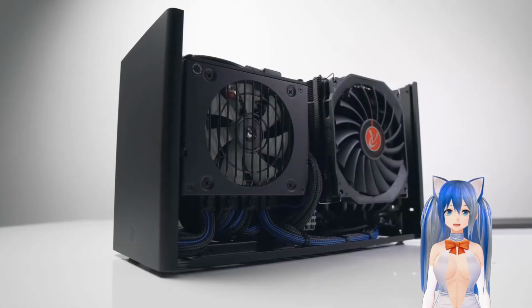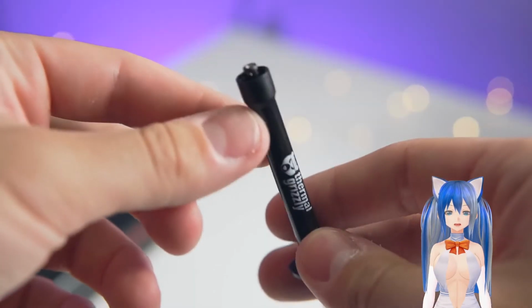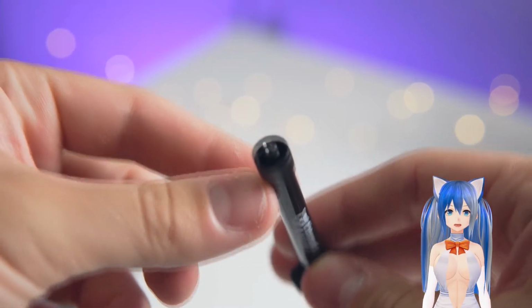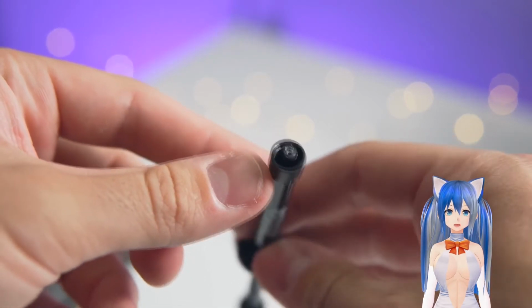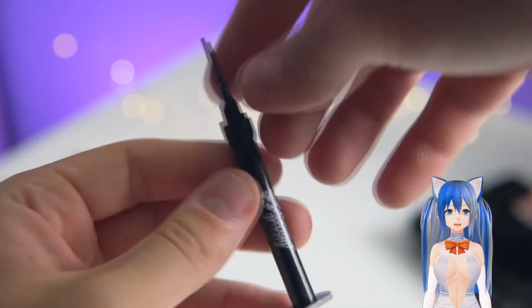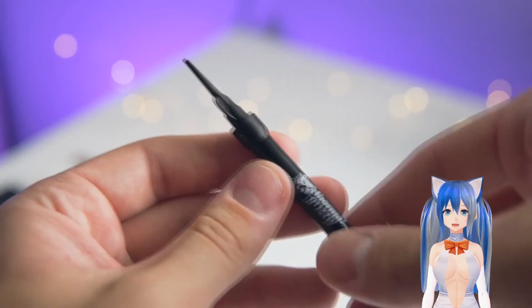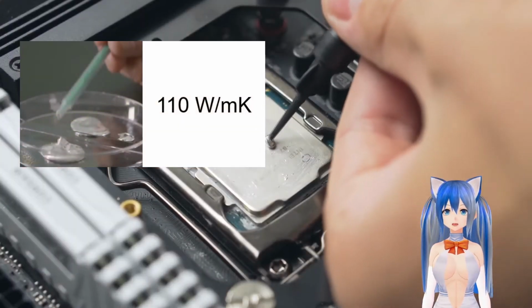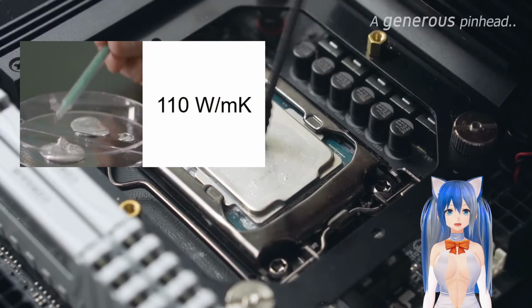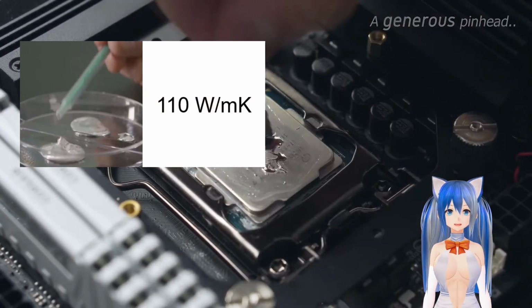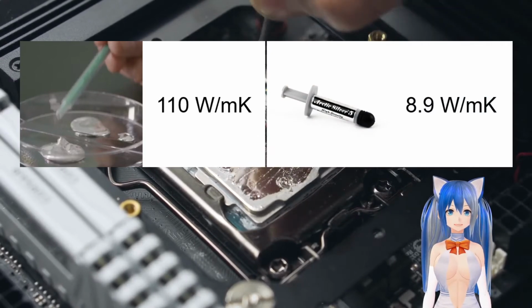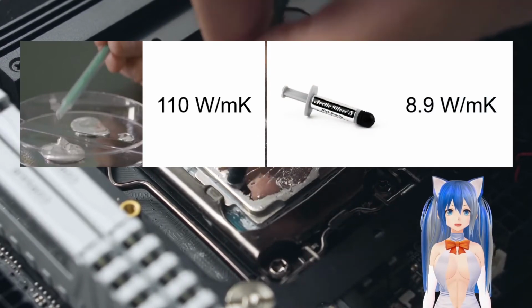Perhaps the most exciting property was the high thermal conductivity of the composite when diamond particles were incorporated into the material. The thermal conductivity experiment showed that the diamond-containing composite had bulk thermal conductivities of up to 110 watts per meter Kelvin, with larger filler particles yielding greater thermal conductivity. By comparison, Arctic Silver Premium Thermal Paste only has 8.9 watts per meter Kelvin thermal conductivity.